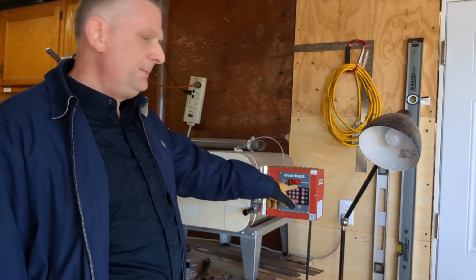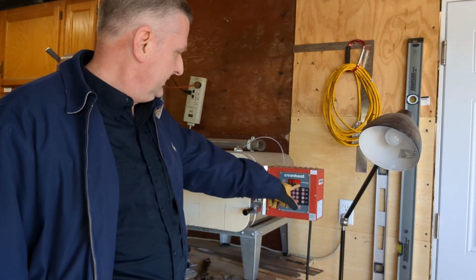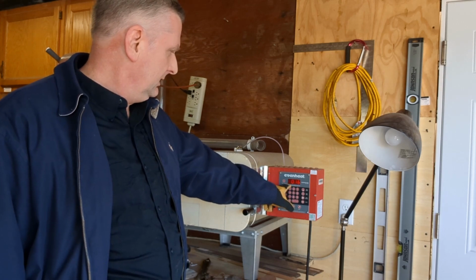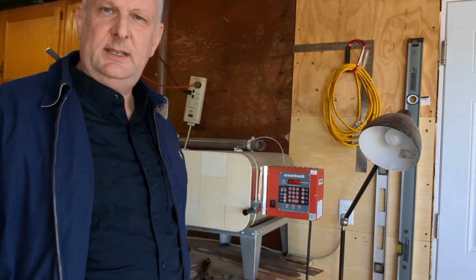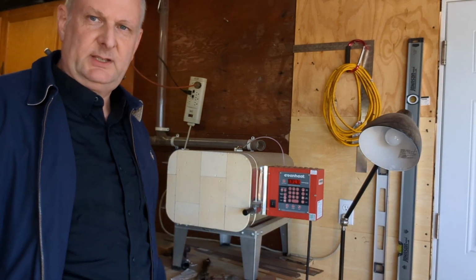So the next step after hardening them will be to let the knife oven cool down all the way and then put them back in for 2 tempering cycles for 2 hours each. And that'll pull the hardness back to where I want it for the knife. Okay, we've reached our temperature. And you can see here, 1196. It's got 16 minutes left to go of the 20-minute soak at 1200.